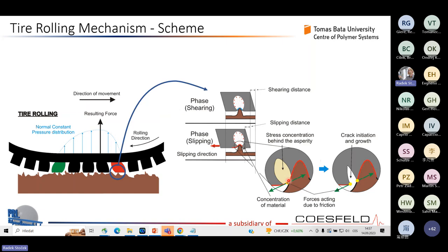In this direction, the rubber is stressed. And then, orthogonally to this force direction, a crack driving force occurs. Therefore, a crack proceeds in this direction, the crack will be initiated and propagates, and during the rolling there will be a next phase, which is run out, that is after the release, here in that part. So a worn particle will be released from the rubber block or rubber matrix. Such a worn particle can be created and emitted into the environment, as Professor Giere explained previously.